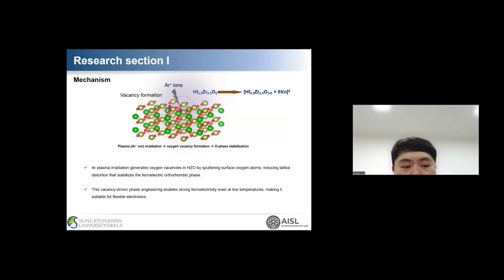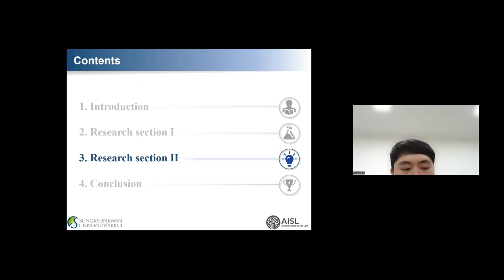In summary, argon plasma modifies the HZO structure through its kinetic energy, inducing reduction in the material. During this process, oxygen is removed from the oxide, creating oxygen vacancies and causing local structural distortion. When crystallization occurs under these conditions, the orthorhombic phase is preferentially formed. Therefore, plasma treatment provides a viable approach to form ferroelectric phase at low temperature. Next, we applied the fabricated HZO to device application.